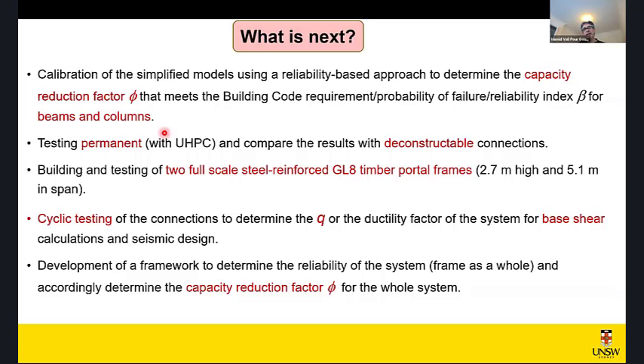For example, there is inherent fire resistance in those ultra high performance concrete joints. We wouldn't be too worried about exposure to fire and vulnerability of the whole frame or connections to elevated temperature. But yeah, they become permanent connections, as I said. But ultra high performance concrete definitely would be the way we're going to test it. And we hopefully test the first series of our specimens, which are 8, by sometime mid-September, and by then I will have the test results. But I'm fairly confident those are the stiffest ones.